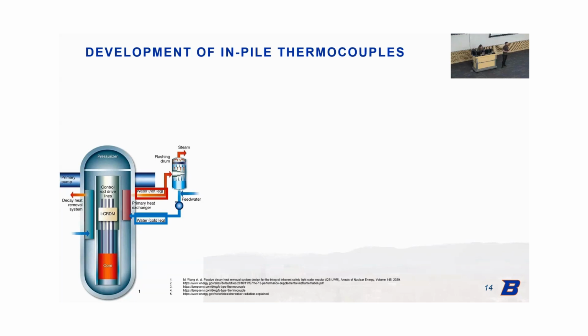Now, what we wanted to do in collaboration with Idaho National Laboratory is develop a temperature sensor for directly measuring the core temperature. One that would provide reliable and accurate real-time data to reactor technicians, not just in general operation, but also during accident scenarios where we can start seeing fuel temperatures in excess of 1300 degrees Celsius. That way we can provide reactor technicians with as much information as possible in regards to the goings on within the reactor so they can make informed decisions.